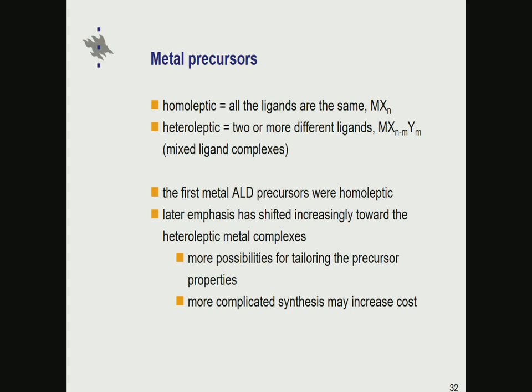Now looking back to the history of ALD, I will do it starting in the very next slides. The first metal precursors were homoleptic, for the simple reason that mostly only homoleptic ones were available at those times. But later, including today, the emphasis has shifted more and more towards heteroleptic metal complexes, because by combining these ligands in a clever way, one can tailor the precursor properties quite a lot. On the other hand, that also means that the synthesis of these molecules gets more complicated, and that translates to higher cost.